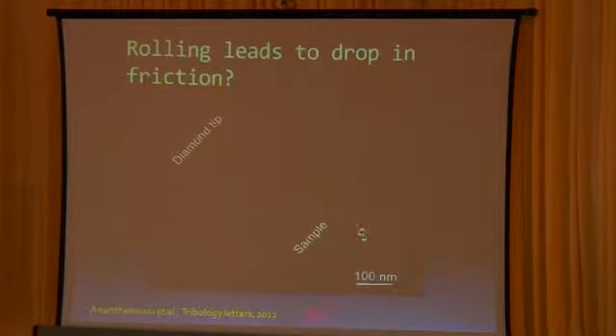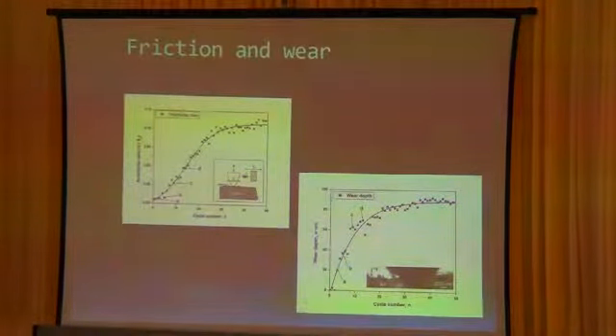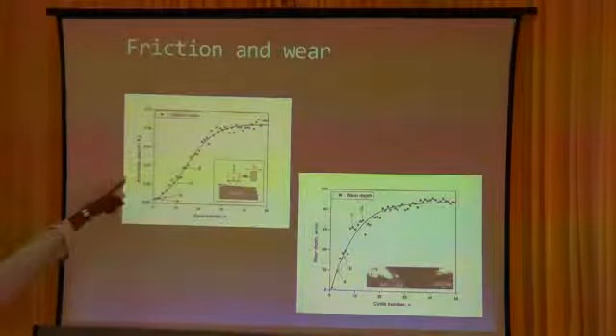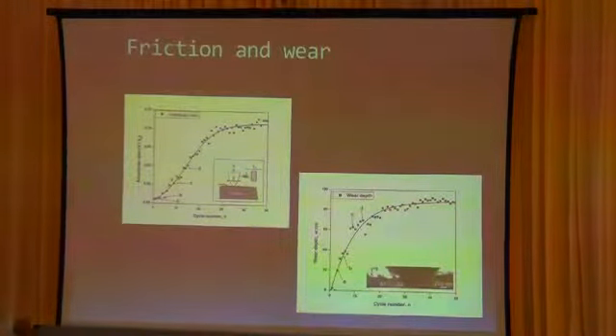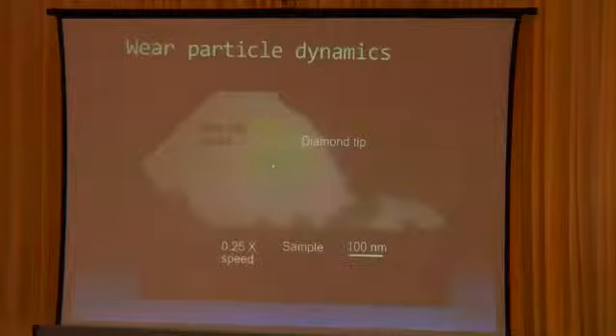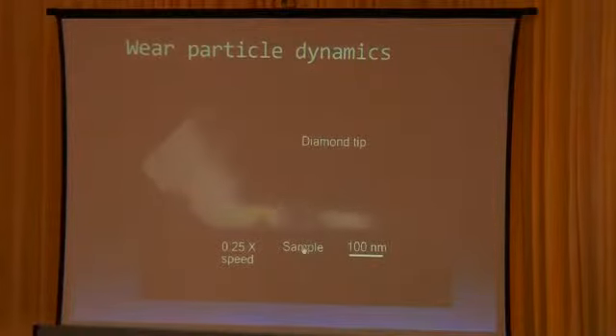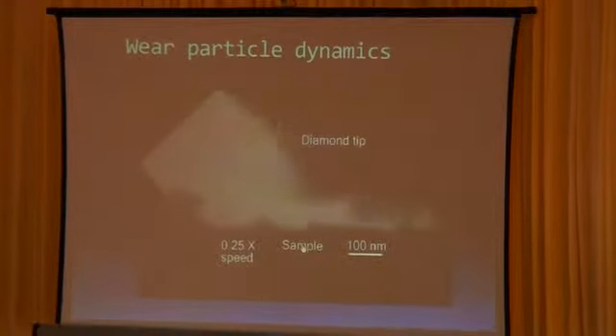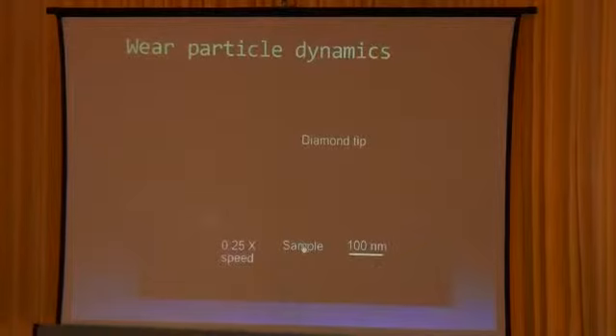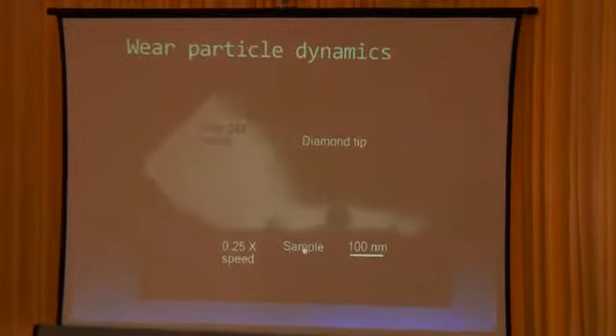Okay. So this is showing how the friction amplitude ratio is inversely proportional to friction, how the friction changes as the wear debris increases. Okay. We can study what happens to the wear particle. This is the slow motion to show that the rolling is setting in. They just roll, join with other particles, agglomerate, dissociate and form many particles.